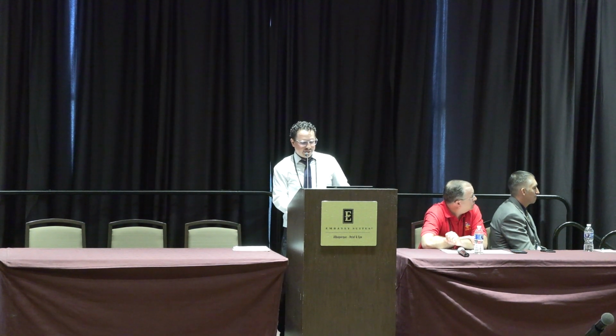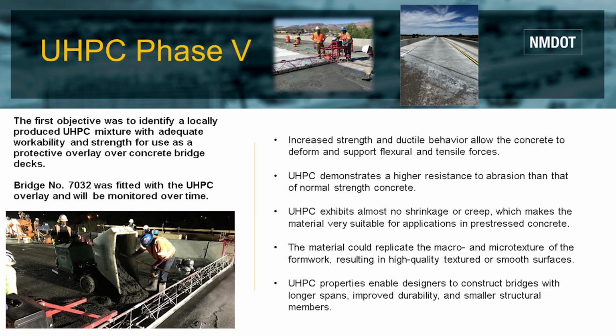So we know some of the benefits of UHPC. It has increased strength and ductile behavior and allows the concrete to deform, supporting flexural and tensile forces even after initial cracking. UHPC demonstrates a high resistance to abrasion and is much better than that of normal strength concrete. UHPC exhibits almost no shrinkage or creep, which makes the material very suitable for applications in pre-stressed concrete.